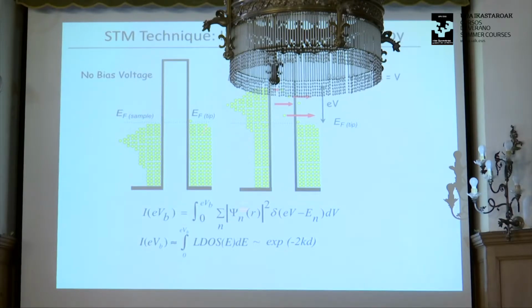And you can immediately see, even pictorially, that the number of tunneling electrons must be proportional to the integrated density of states of both the sample and the tip from the Fermi energy, right, to whatever the bias voltage, from the Fermi energy to the bias voltage. That's it. So the tunnel current is proportional to the integrated density of states from the Fermi energy, which we call 0 always, to the bias voltage.